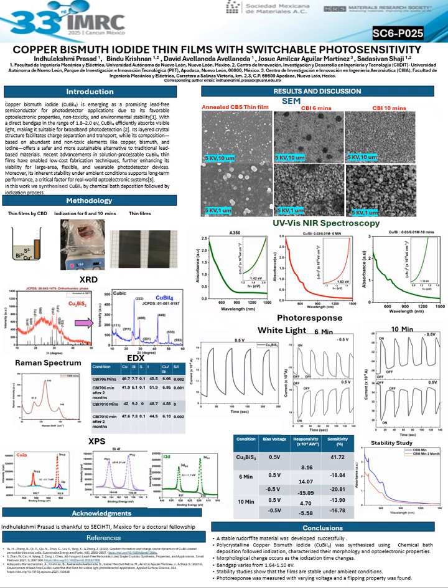We also studied the characterization by XRD for analyzing the phase and the stoichiometry of the material. First we analyzed the copper bismuth sulfide, and we found it is an orthorhombic phase having a stoichiometry of Cu2BiS2.